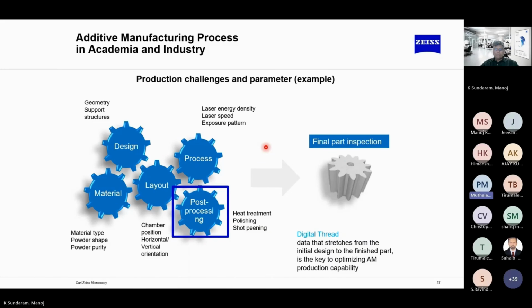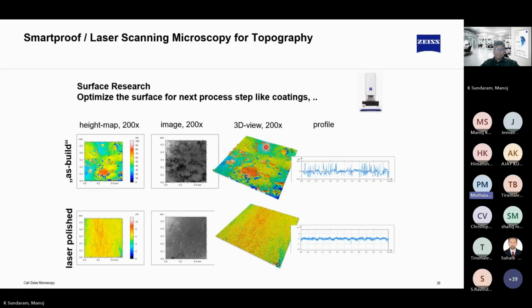And the final part is inspection, post processing. Not only powder characterization, defect identification of voids and pores, and EDS analysis, we can also do non-contact surface roughness analysis. When we have 3D printed parts, the surface is similar to a matte finish. And depending on the applications, you need to maintain the roughness parameters. So how will you analyze the roughness parameters?